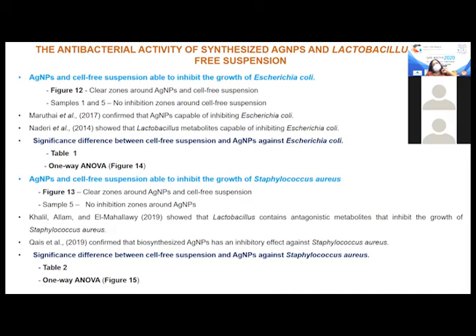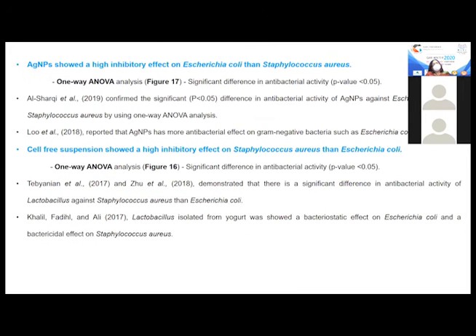Silver nanoparticles showed a higher inhibitory effect on E. coli than S. aureus. So why? This might be due to structural variations in the cell wall, because gram-negative bacteria contain a thin layer with charged lipopolysaccharide, which is more susceptible to attraction by the positive charge of silver nanoparticles. Also, silver nanoparticles deteriorate the cell membrane, interfere with cellular functions, interact with the DNA, and induce oxidative stress.